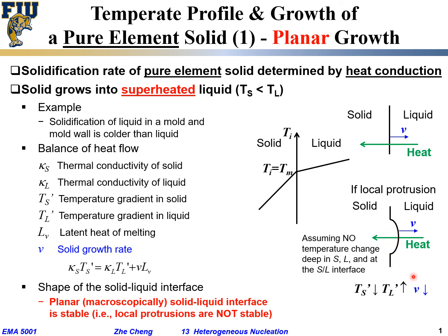Okay? So that is the first scenario, of solid growing into superheated liquid, meaning the liquid side is at a higher temperature than the solid side. That's what we mean by superheated liquid. And in this case, we would obtain planar growth. The interface microscopically would remain flat, meaning any protrusion of solid into liquid, even if it appears, would quickly disappear, because it will grow at the tip slower compared with the other remaining flat region. Okay?